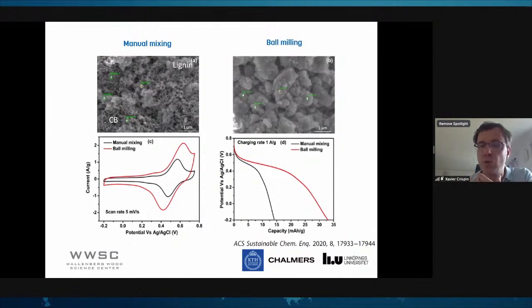So it means that you succeeded to bring your carbon in the nano dimension in the lignin. And then what you obtain is a much larger contribution for the lignin, because there is more lignin accessible now with those tiny conductors that you have formed mechanically. The storage capacity is also more than doubled in that way.